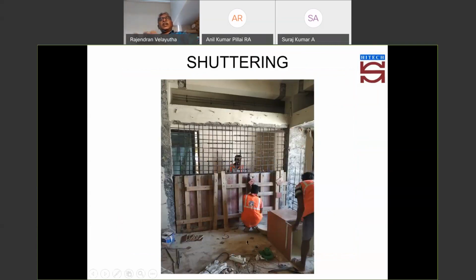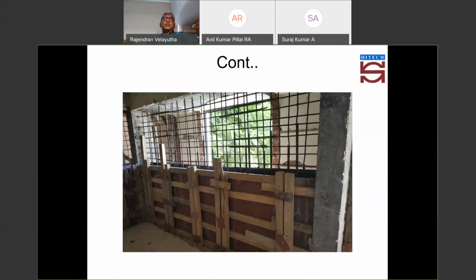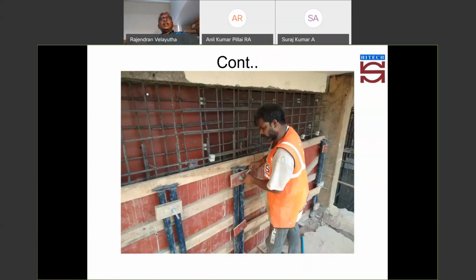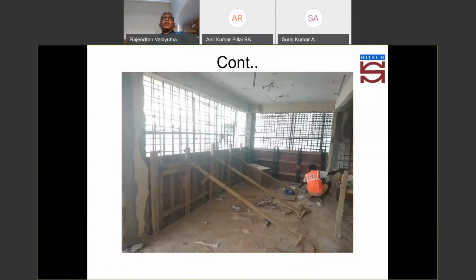This has been followed, and again waterproof ply formwork has been provided. With respect to concrete, we cannot go for a normal concrete, because the first lift has been done and the second lift will go up to the top of it. If I want to do normal concrete, then I have to do the vibration. When I want to do vibration, I have to use a 40 millimeter needle. This will be about 450 mm long, and then I need some working space, another about 300 mm.